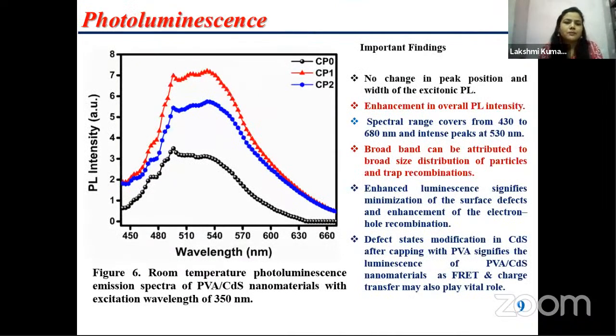studied its photoluminescence property. From the photoluminescence property, we can see we have excited this material with an excitation wavelength of 350 nanometer. There is no change in peak position and also width. Almost they are similar in all samples, but there is more enhancement in overall PL intensity. And the broad band can be attributed to the broad size distribution of particles and trap recombination, which I have also seen in the histogram plot of this material.